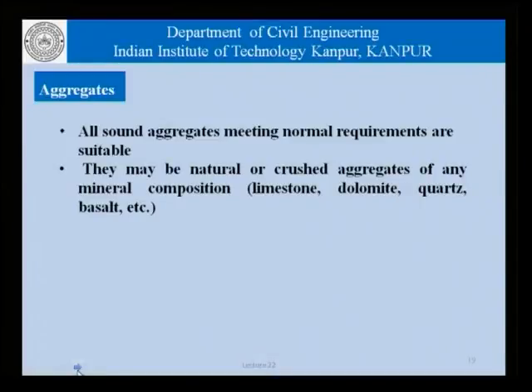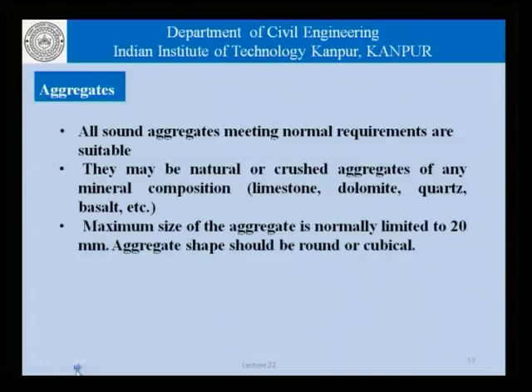These aggregates could be natural or crushed aggregates of any mineral composition, limestone, dolomite, quartz, basalt, whatever, except that the usual rules as far as alkali aggregate reaction will apply. We do not want to use reactive aggregates. As far as the maximum size of the aggregate is concerned, that is normally limited to about 20 mm, and aggregate shape should be round or cubical.